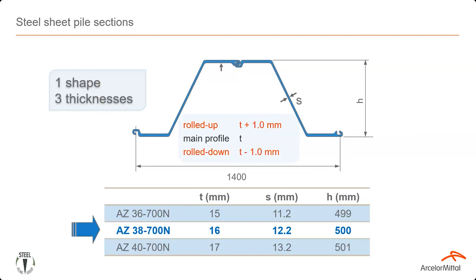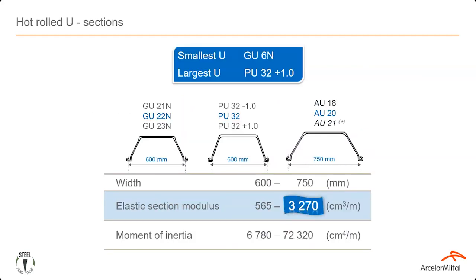Now the piles, they come in families of 3 or 4. To give you an example, for an AZ 38-700N, we can roll 1 mil thicker and we get a 40-700N, and we can also roll 1 mil thinner and we get a 36-700N. N is just short for new, it means it's our latest additions.